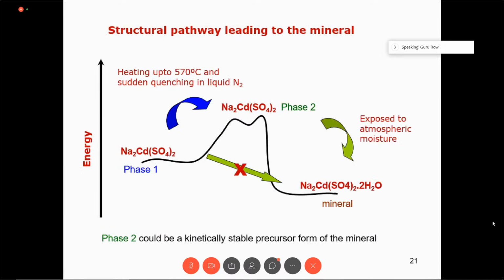So what is the procedure? What we found out was that if we take the sodium cadmium sulfate, the phase 1 as I call it, and heat it up to 570 degrees, and then suddenly quench it in liquid nitrogen, we get a different form of Na2CdSO4 twice. This we call phase 2. And this, when exposed to atmospheric moisture, will form the mineral. So this is a remarkable pathway.